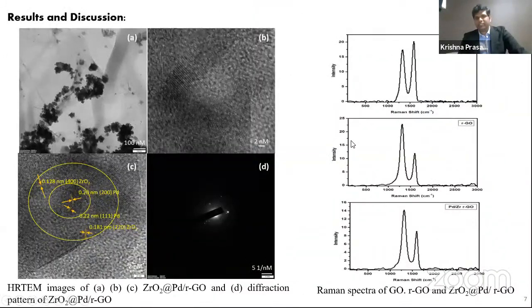Yes, sir. Actually, we have recorded the Raman spectrum and it is presented here. This is for the graphite oxide, that is after the Hummers method. And here we can see the Raman spectrum for the RGO, that is the formation of graphene after chemical reduction using hydrazine. And here we have seen that there is a significant increase in the intensity of the D band with respect to the G band, which is a confirmation for the formation of chemically reduced graphene or few layered graphene.